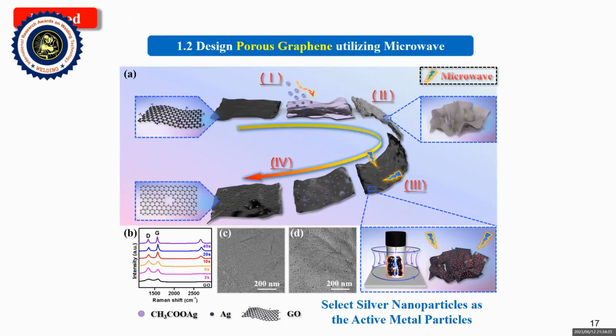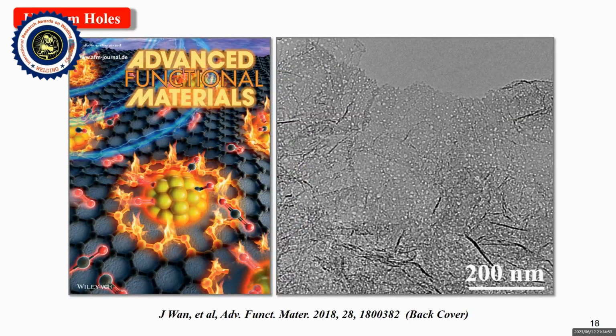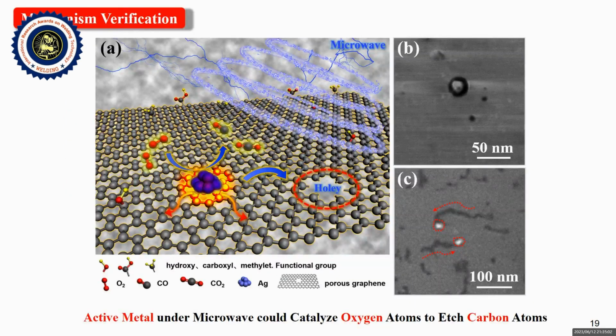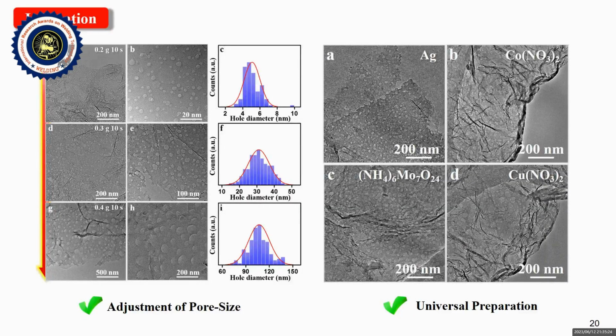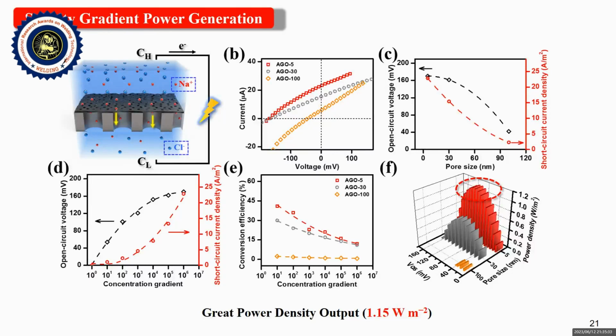We selected silver nanoparticles as the active metal particles, which easily form round particles. By etching graphene with microwave, we can design porous graphene. As shown in the TEM images, the pore size of this porous graphene is very uniform and even beautiful. Through mechanism verification, it is confirmed that the active metal under microwave could catalyze oxygen atoms to etch carbon atoms. Moreover, we can also realize the regulation of pore size and universal preparation. The porous graphene with different uniform pore sizes could show excellent performance in salinity gradient power generation.